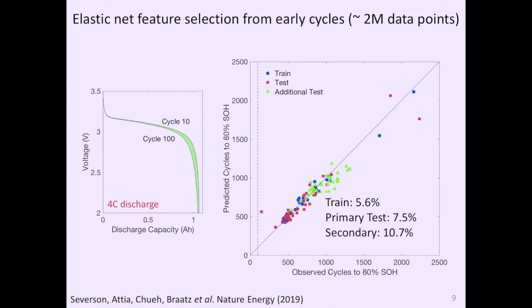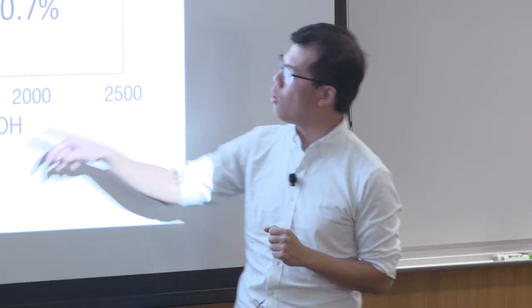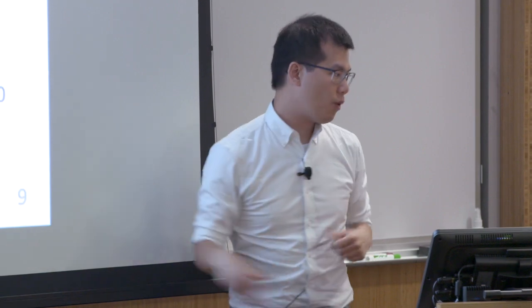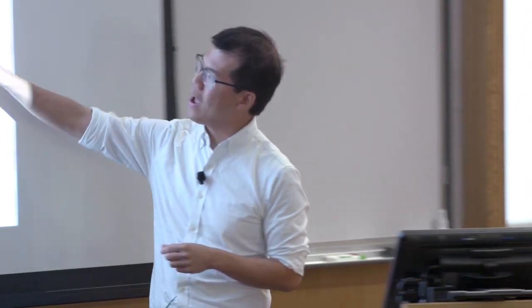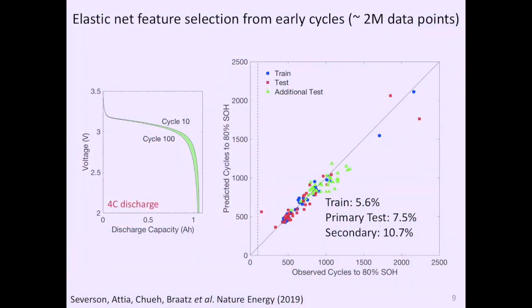And we ran a very simple machine learning exercise using a methodology called ElasticNet. This is 20 years old, nothing fancy. But we take the 10th and the 100th cycle, so just two cycles, and we train the model to predict the lifetime all the way out to 2500. And we're able to achieve a level of prediction, just using 100 batteries, of around 10% error. Okay? So that means we can predict with 90% confidence what is the battery's lifetime by just recording this amount of data. So this will then translate on average into a saving of 15x just by not having to cycle the battery to failure.